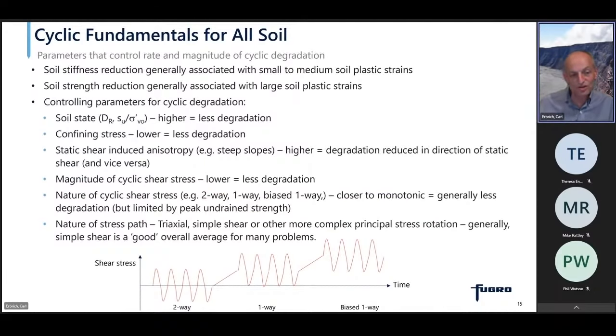So what parameters control the rate and magnitude of cyclic degradation? So here we've got a list of some of the key ones. Soil stiffness reduction is generally associated with small to medium plastic soil strains, whereas soil strength reduction is generally associated with large plastic soil strains. And the things that control that are soil state. So as I mentioned, relative density, Su on sigma V, or the state parameter in terms of void ratio, at least in terms of Su on sigma V and DR, a higher value of these will lead to less degradation.